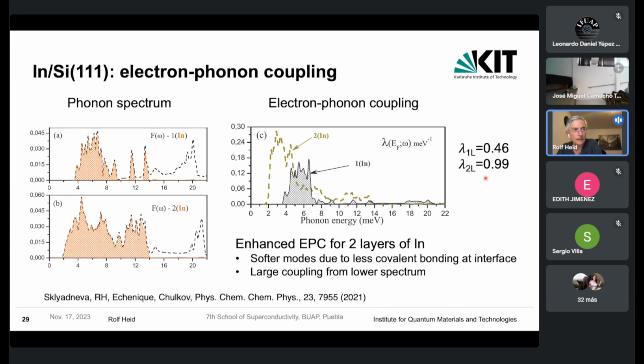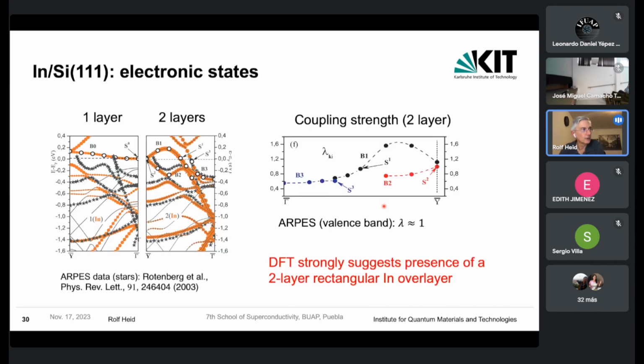And only the second one is sufficiently large to explain the observed Tc of about 3 Kelvin. So in that respect, these calculations also indicate strongly that we indeed have in the experiment a 2 monolayer system, and not a 1 monolayer system present. We can go further and compare that with ARPES data taken on such systems.